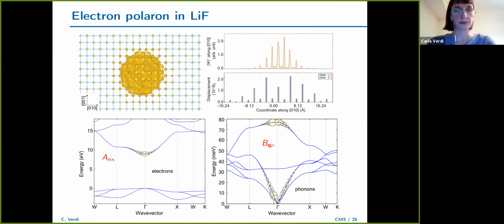Remember, what we did was expanding the polaron state in terms of Kohn-Sham states and the atomic displacement, sorry, in terms of phonon eigenvectors. So if we plot the expansion coefficients on top of the electron and phonon band structures, this is what we get. What we get is basically a quantification of what are the electronic and the phononic states that really contribute to this polaron. So what this tells us is that the large electron polaron in lithium fluoride is mainly composed of states near the conduction band bottom, and the phonons that take part in it are mainly the long-range longitudinal optical phonons.